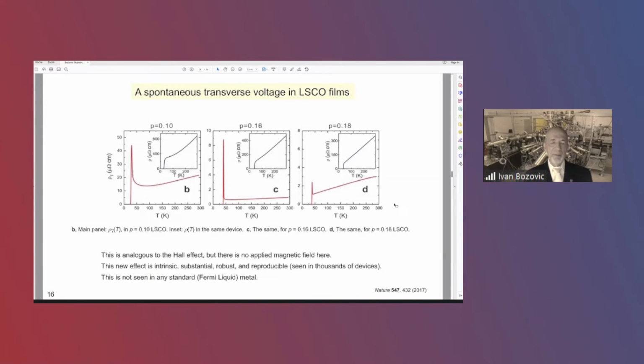And here are some representative results for 3 lanthanum strontium cuprate films: underdoped, optimally doped, and overdoped. In each film, you see that a spontaneous voltage appears transverse to the probe current. This is just like a Hall effect, except that there is no magnetic field here. What transverse voltage means is that electrons feel some lateral force, which is compensated by the electric field from the charges that pile up at the Hall bar edges. Now, if the material is tetragonal, the resistivity tensor is isotropic and there is no lateral force. However, if the material is orthorhombic, then the conductivity is highest in one direction, and if you force the currents to flow in a different direction, then there must be a lateral force and hence a transverse voltage. So that's the idea.